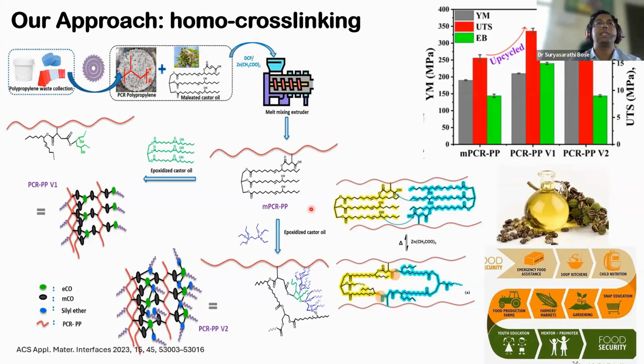So this compound, which is called PCR-PP with certain ingredients, is a little special from what you saw in the last 2 slides. This oil helps in homo-cross linking, which means that the 2 chains of polyolefins are not only connected with this molecule, but they also form some homo-cross linking within them. So this helps us to control the MFI, and therefore in our PCR PP, we were able to control the MFI, whereas in the literature, most of them reported the MFI shoots up.